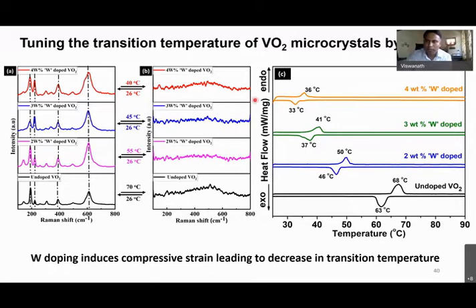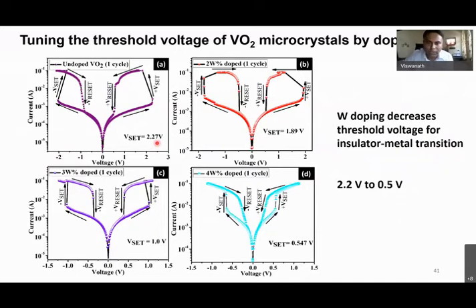We have again made VO2 microcrystals doped with tungsten. I think the DSC will be straightforward. Compared to the undoped one having a 68 degree phase transformation temperature, systematically we can see it is going to 50 degrees Celsius, 41 degrees Celsius, 36 degrees Celsius as we change the doping concentration. Again, how do you know there is a clear phase transformation? We also confirmed with Raman spectroscopy that the phase transformation temperature indeed changes with respect to the doping.